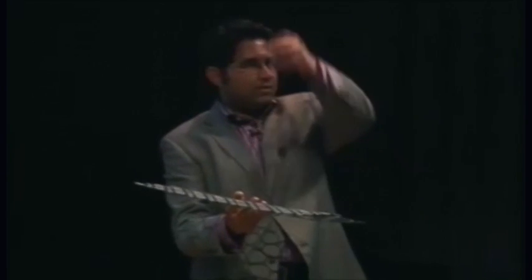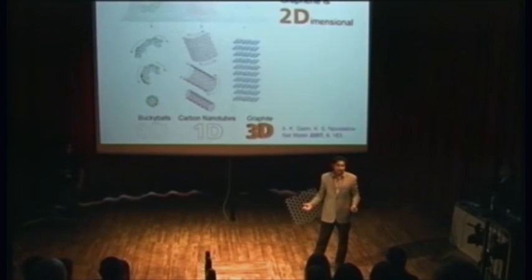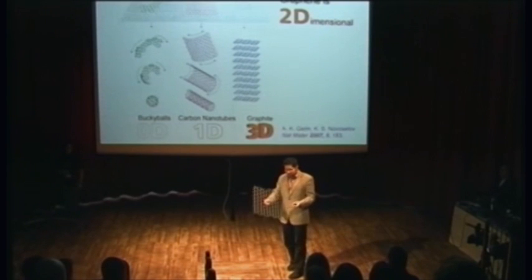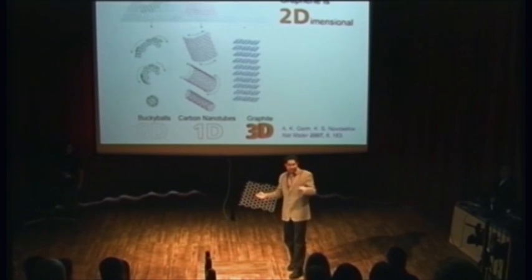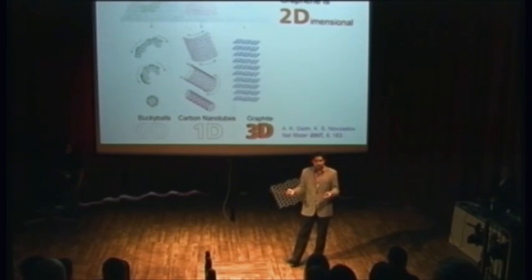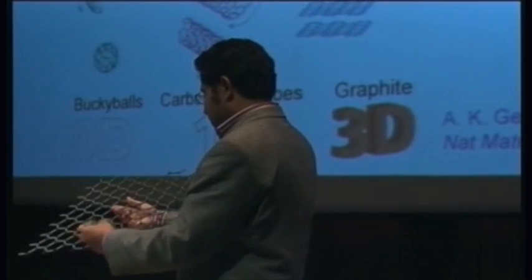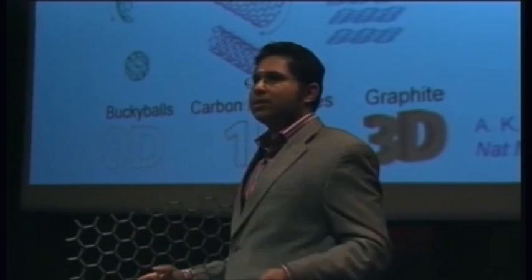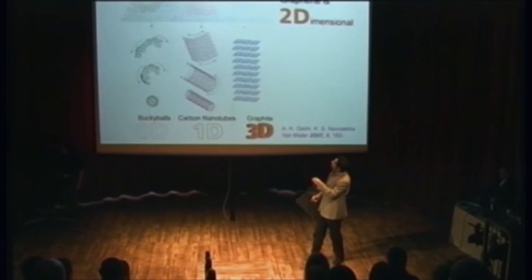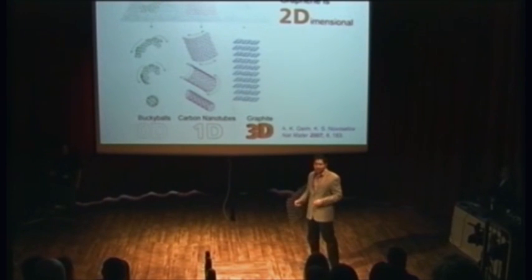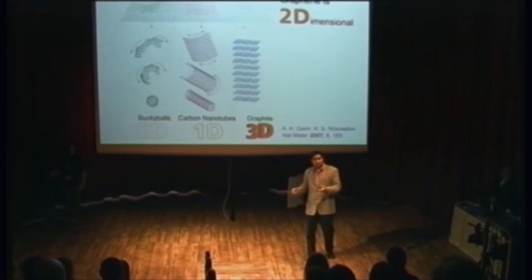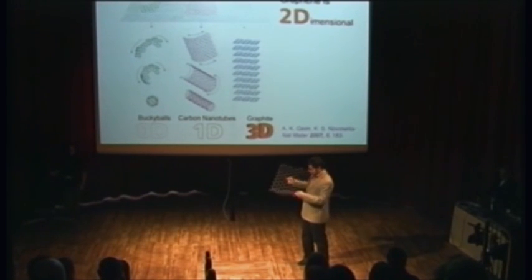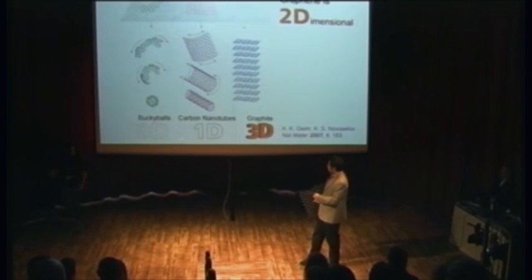Graphene is also the fundamental building block for a number of different materials. If you take a sheet of graphene and stack one sheet on top of another, you get graphite — which is pencil lead. What happens when you write with a pencil is that these sheets shear off and form black traces on paper, and some of those pieces are single layers of graphene. If you roll the sheet up into a tube, you get a carbon nanotube. If you cut it in a very special way and roll it up, you can get a sphere called a buckyball or fullerene. The buckyball is zero-dimensional, carbon nanotubes are one-dimensional, graphite is three-dimensional, and graphene is two-dimensional.